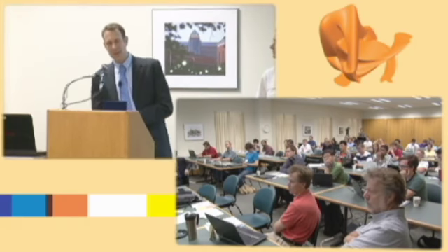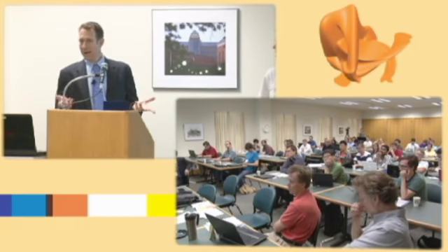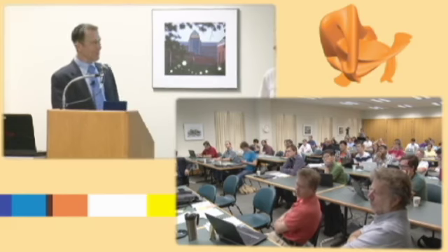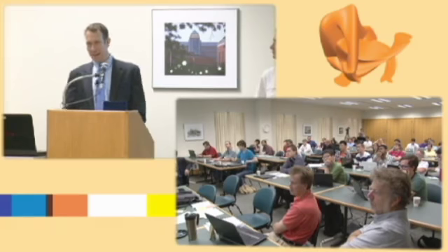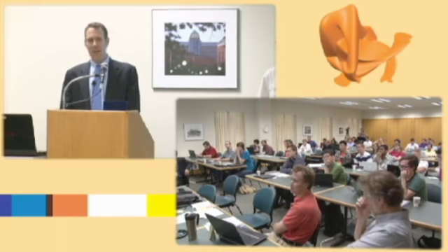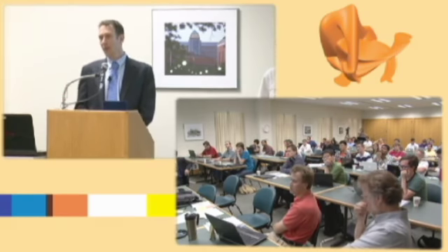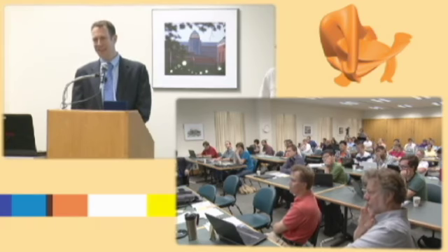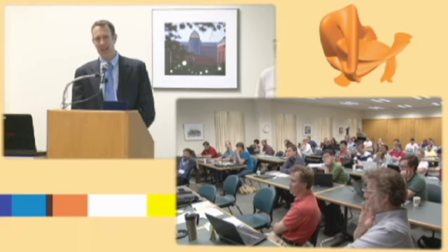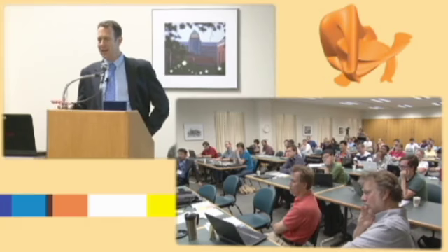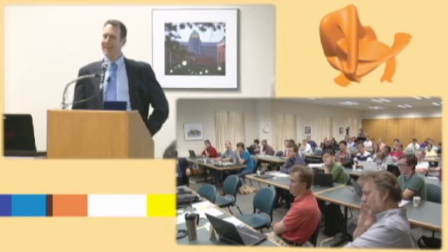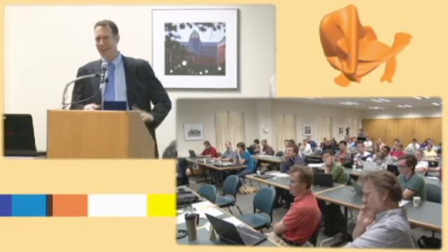I didn't do that work. That was done by Kornev and Balazs. We repeated their calculations and got the same results. We tried different density functionals, and they all gave the same results. So we said, this is a great thing for our experimental colleagues to do. Over the last 5 years, we've done a series of more and more sophisticated high-pressure experiments, and none of them have shown this high pressure ferroelectricity. We said, maybe it's because the calculations are done at zero temperature and the measurements at room temperature. So we did cryogenic measurements at 10 Kelvin and still don't see it.